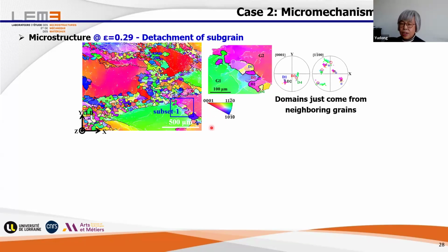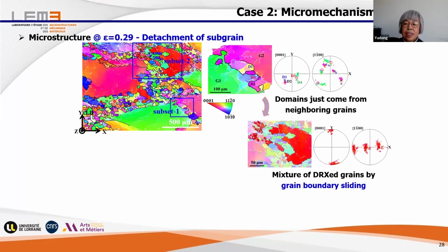And then we say it's not a new nucleation for this kind of recrystallization. It's fragmentation from the parent grains, parent coarse grains. And then we ask further, for such things, how did it happen? And then we made analysis here, only with the pole figures. You see how powerful it is. You see, this is the parent grain, the red grain. And the small grains here, their orientation is very close to their mother grain, but they are physically detached from their mother grain. And so this allows us to see there's grain boundary sliding happening.